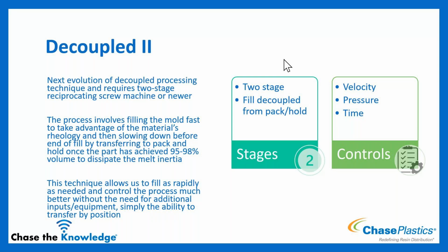and then we're going to initiate a pack under pressure control. So this technique then allows us to fill much more rapidly because we don't have to worry about the inertial overshoot of filling the cavity because we're purposely going to leave the cavity with a small amount of volume in it so that we can account for that under the pack phase. So that fully lets us take advantage then of polymer rheology in shear thinning to increase repeatability. And then we can pack separately. So again, this is a two-stage process. And now fill is completely decoupled from pack and hold. And again, velocity, pressure, and time are our control variables here.